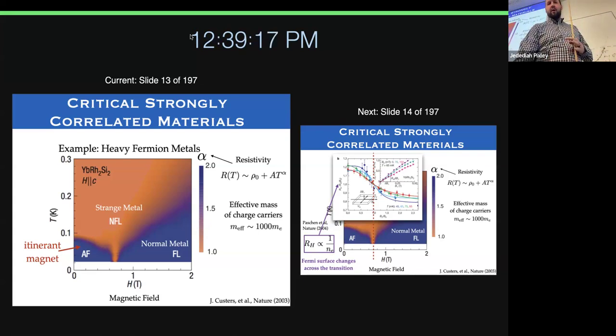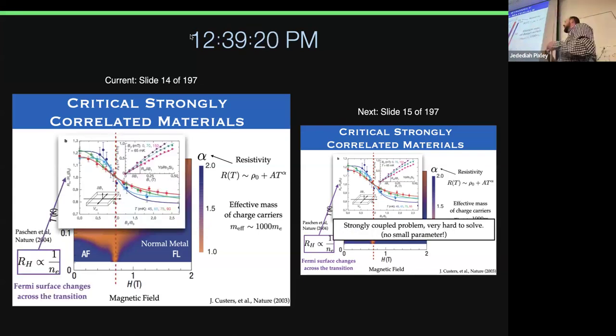But moreover, what's really amazing about this transition is if you look at the size of the Fermi surface on one side and the other, this Hall number is proportional to 1 over the charge carrier density in a Fermi liquid. As I showed you here and here, I have a reasonable Fermi liquid, so I can associate this to the size of my Fermi surface. And as you can see here, I'm going from a large to small Fermi surface where the electrons and the local moments become part of the electronic liquid because of that strong coupling situation. Okay, and describing this change in the Fermi surface along with this symmetry breaking is still challenging the field today.